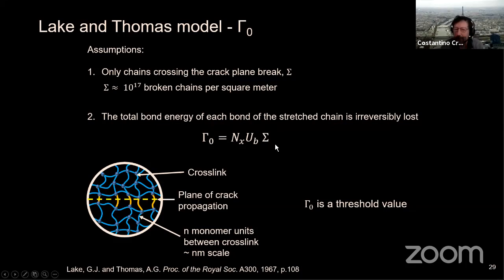That makes sense. You break covalent bonds. This U_B in the original Lake Thomas model is the energy of any one of these bonds in the chain, in the yellow chain. And what they added, which is different from the normal fracture model, is this N_x, the number of monomers in the chain. So what they assumed is that you need to fully stretch the chain before you can break it, which is reasonable. We assume the same. And that when you break that chain, you lose all the energy.